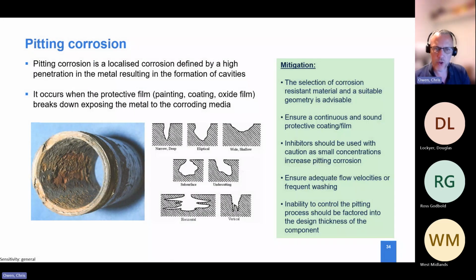Pitting, so going back to the thin wall tube, pitting occurred because we saw rapid acceleration in a very localized place. So again, pitting is normally as a result of something which has either happened on the surface of the tube. Either there's a defect there or there's a localized breakdown. It could be that pitting takes place because of another corrosion reaction called MIC, microbiologically induced corrosion, where debris or biofilms build up on the internal surface of the tube. And you can see from the diagrams here that there are lots of different pitting mechanisms which take place. And again, this goes back to the steel chemistry and the grade of steel which has been specified. But again, there's lots of things which can be done to mitigate the risk of pitting corrosion taking place.